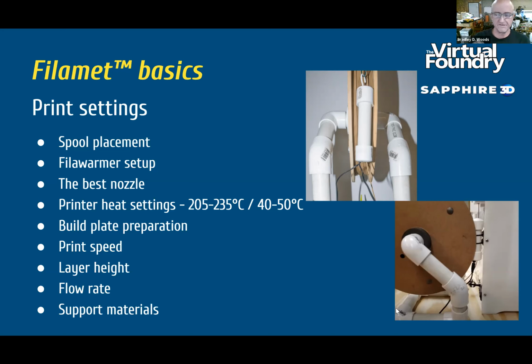Our material is not as strong as plastic. It isn't going to be. It can't be. It's loaded with so much additive that the key struggle in manufacturing over the past few years was developing a polymer that would hold the material together well enough that it could be handled, yet have enough metal powder in it that it will sinter properly. So once you get it through the Filawarmer, though, it's quite stable, and it will make it through the printer.